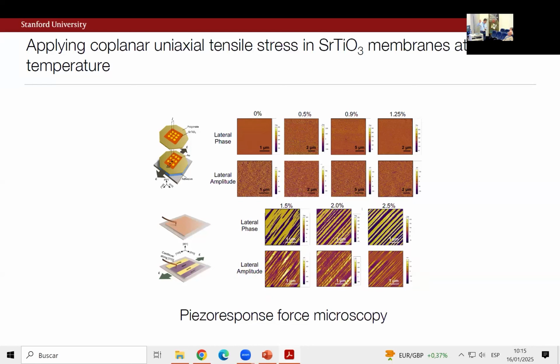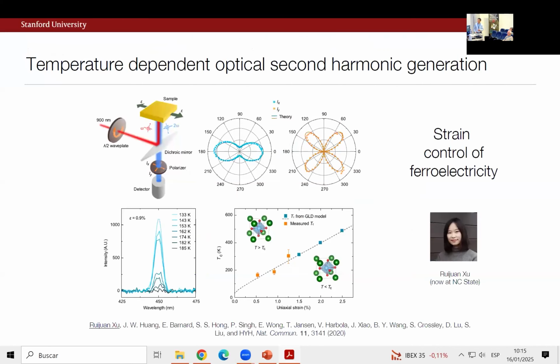So I should say that there's been a long history of using strain and pressure and isotope, et cetera, et cetera. So this was presumably somewhere where we thought, again, we would have this instability nearby. In addition to PFM, actually in collaboration with people at the Molecular Foundry, quite close to us across the bay at our Berkeley lab, one also studied as a proxy for the onset of ferroelectricity, the breaking of inversion symmetry by using second harmonic generation, right? And looking at the symmetry of that response.